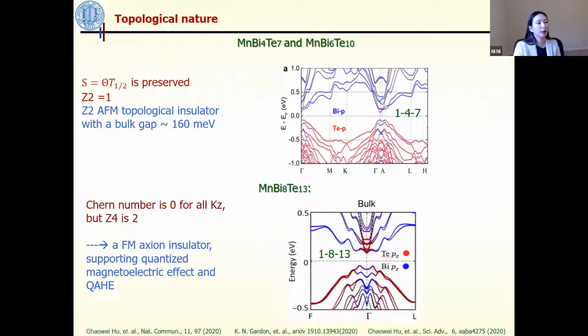To identify its topology, DFT calculations and ARPES measurements were performed. So you can see for the 147 and the 1-8-13, we can clearly see there is band inversion around the gamma point, which is an indication of possible topological phases. And then our collaborators calculated the topological invariant Z2. And for both 147 and 1610, they got a Z2 number of 1. So this suggests that they are Z2 antiferromagnetic topological insulators.